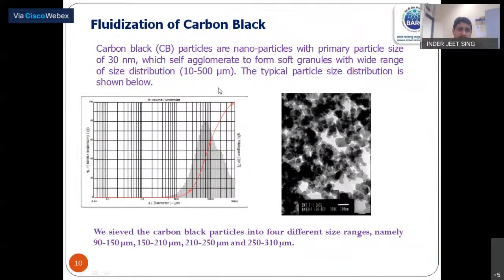So why carbon black? For developing a nanotube, we require some nanomaterial. Now, fluidization of nanomaterial is a difficult thing because agglomerates form, which doesn't allow the nanoparticles to be fluidized very easily. But carbon black is such a material which has a primary particle size of 30 nanometer, but then they self-agglomerate into soft granules with a wide range of micron size. If you see the distribution, it is from 10 to 500 micron. So you can easily fluidize them. So that is why carbon black has been used. It is a nanomaterial, but also easily fluidizable. Secondly, the cost is very low with respect to others like alumina, silica, whose costs are high.